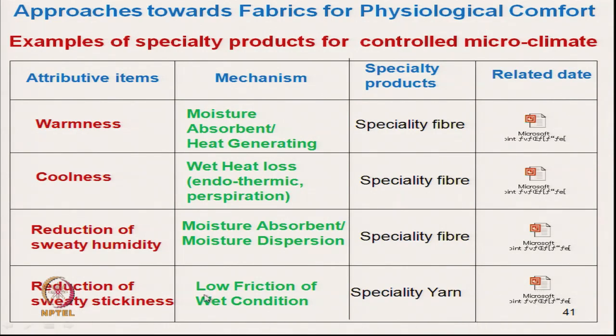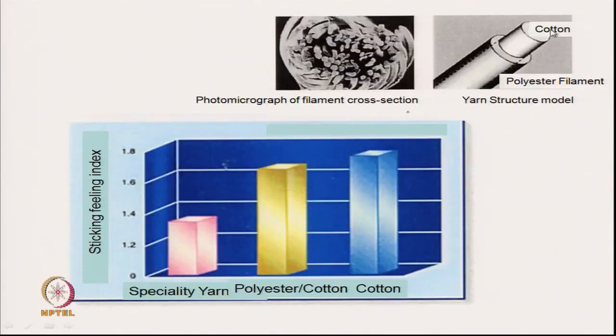For that, low friction fiber has been developed, this is the yarn structure. Normal polyester cotton, this is the friction stickiness index, it is high. Normal cotton, the stickiness index is higher than that, but the developed specialty yarn, the stickiness index is least. Here at the core, cotton fiber is used, and at the sheath, polyester filaments are used. So, if we develop yarn from this combination, we can develop yarn with lower stickiness. So, these are some commercial products.